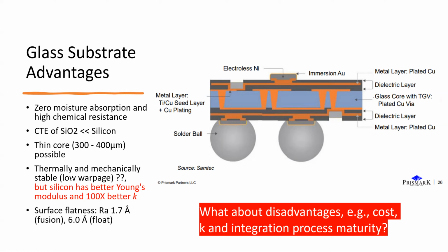And they say they are thermally and mechanically stable. I have a little problem with that claim. This is what they claim. From the thermal and mechanical stability perspective, silicon has a better Young's modulus and is 100 times better in terms of thermal conductivity. So I don't see they can stand on that. I think the thermal expansion gives you potentially lower warpage, but you have a thermal conductivity problem at the same time, right? Heat needs to conduct away. Unless you've done optimization, your heat transfer property is not as good as silicon, even though silicon is a little bit worse in the coefficient of thermal expansion. So these are intertwined problems. You can see that now.